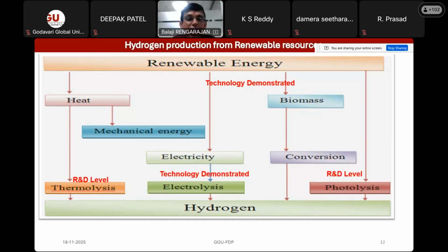the water can be split directly into hydrogen and oxygen at a high temperature of 2000 degrees Celsius. Without any catalyst and without any materials, you can decompose water directly through thermolysis at a higher temperature of 2000 degrees Celsius. You can get hydrogen and oxygen. But during the separation of hydrogen and oxygen, there may be a possibility of recombination at high temperature. Again, it will become an explosive thing actually. So because of that, these thermolysis routes are still at the R&D level.